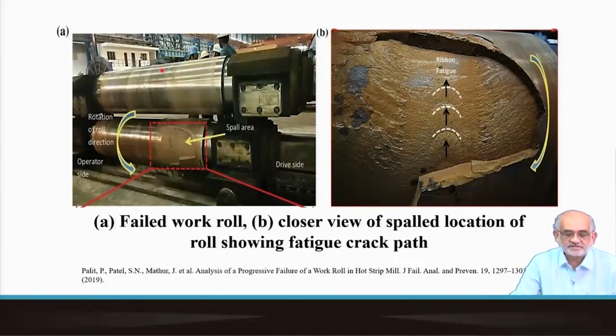But most importantly, if the surface over a period of time either developed or already had right from the beginning residual tensile stress, at least in pockets, then it could lead to such very major and catastrophic failure, where a portion of the surface, as you are seeing here in this red box, is completely spalled off. It broke out of the main surface, rendering the entire roll completely unusable anymore.